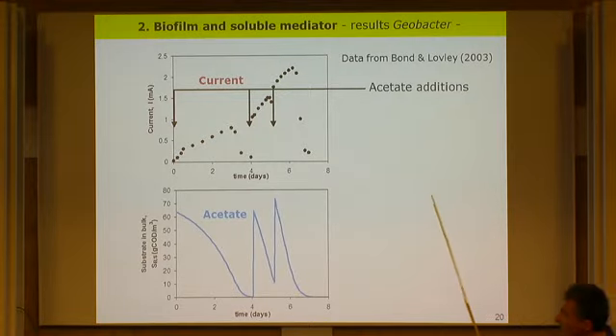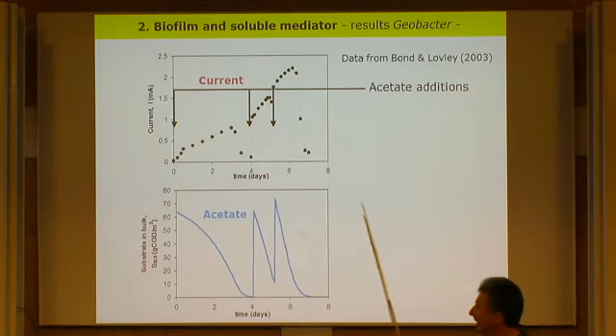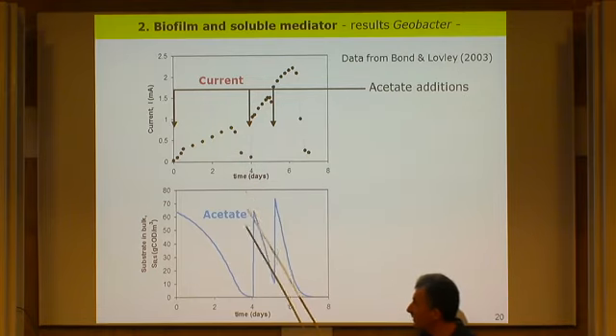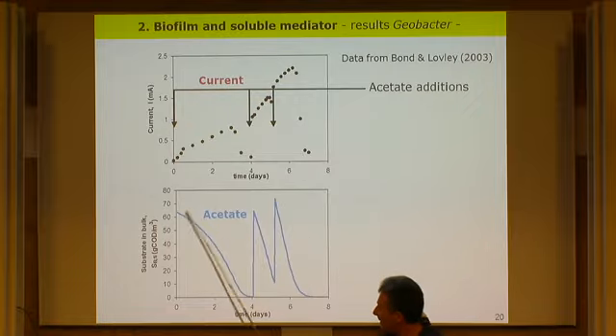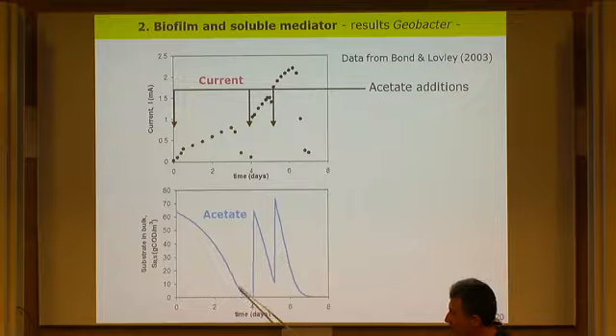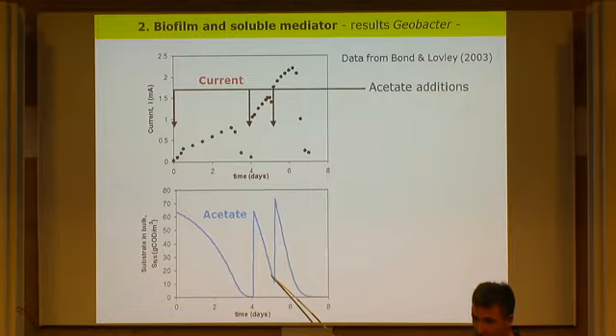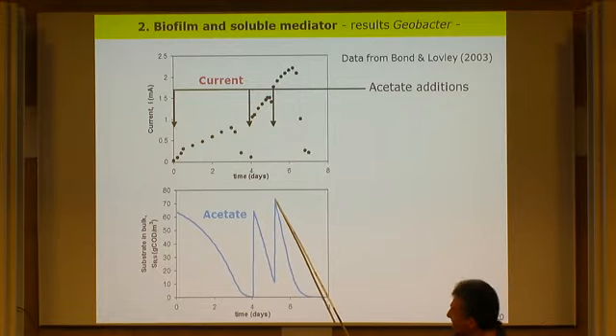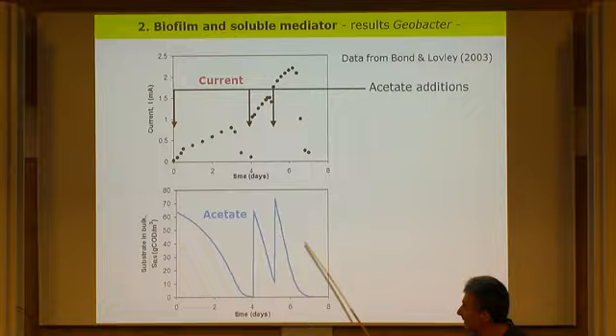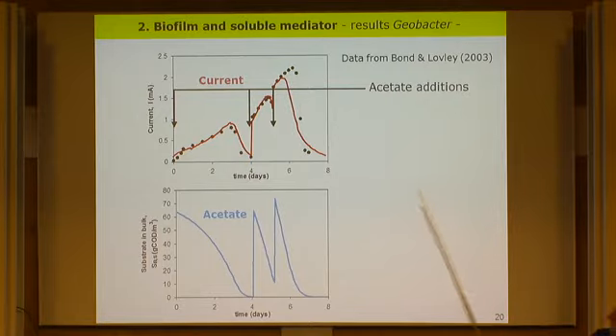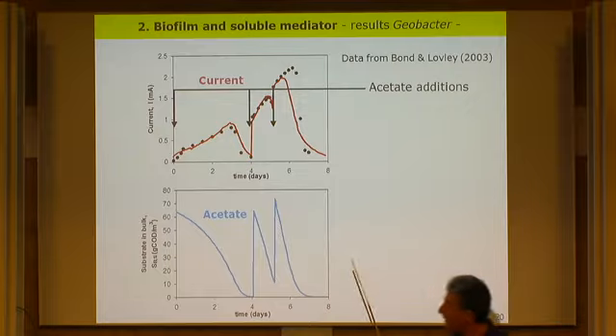And this is what we simulate now. We take this data and we put the acetate in at 1 millimolar concentration. They add it here. The acetate is consumed. This is simulated now. And then you add again, and this time acetate is taken up quicker because there is a thicker layer of cells. You add another batch, and again, even quicker, you have the acetate uptake. And this is how the predicted current looks from this acetate uptake.